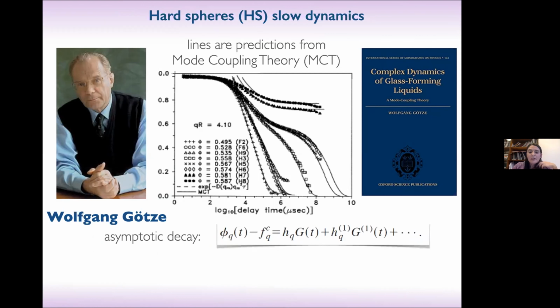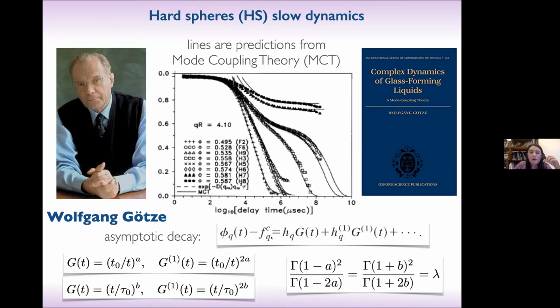An important thing is that mode coupling theory is able to calculate analytically the behavior of the density correlators close to the critical point, so close to the transition. The correlators can be expanded in a series of a given time function, so it factorizes the dependence on Q from the dependence on time. Professor Goetze and co-workers showed that, approaching and leaving the plateau of the transition, this G of t, called the beta correlator because it describes the beta relaxation, has a power law form. It is t to the minus a going to the plateau and t to the b leaving the plateau.